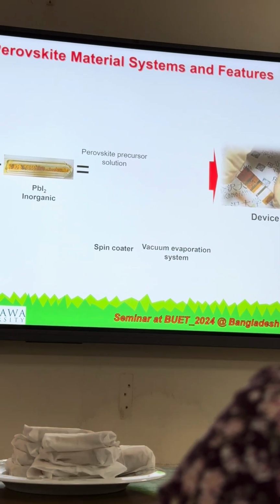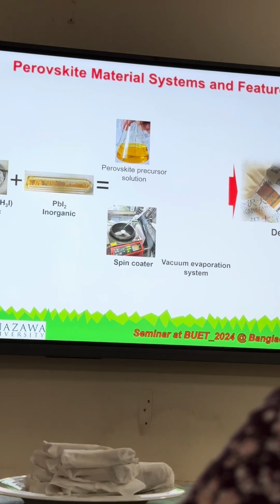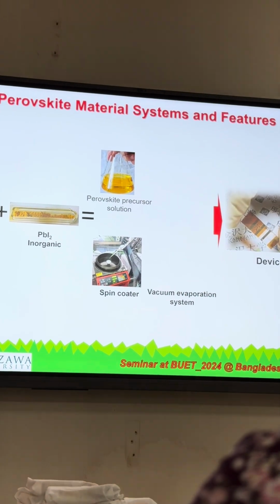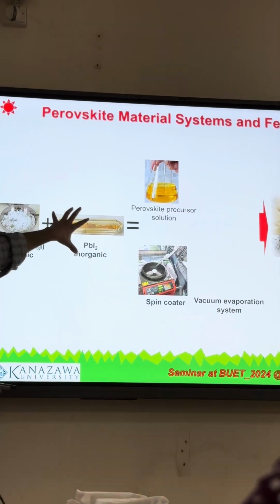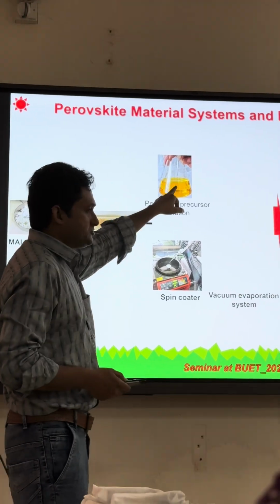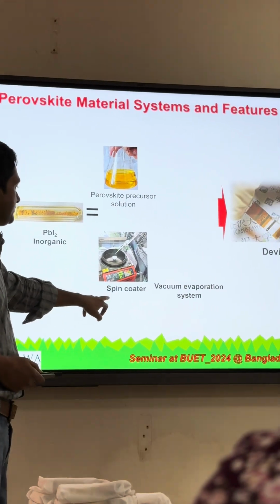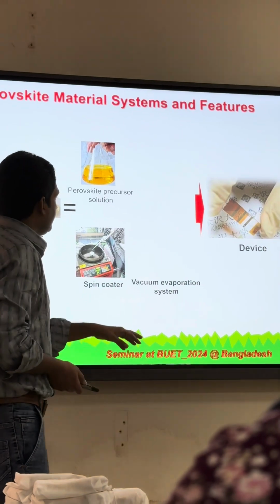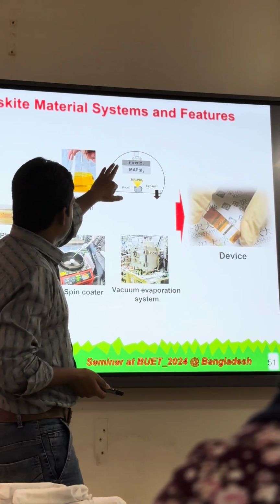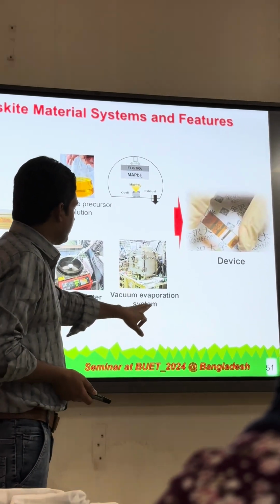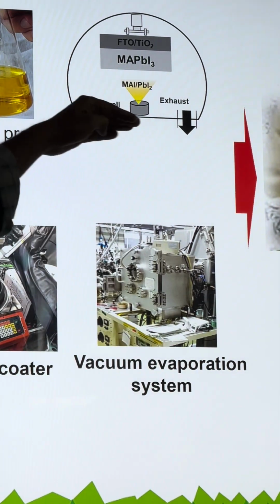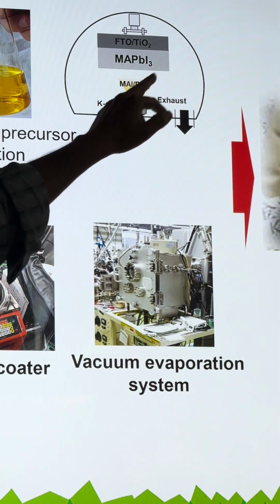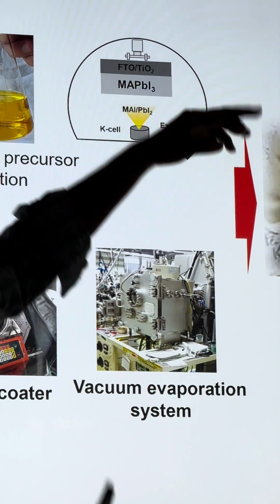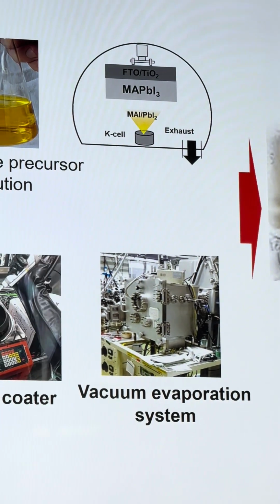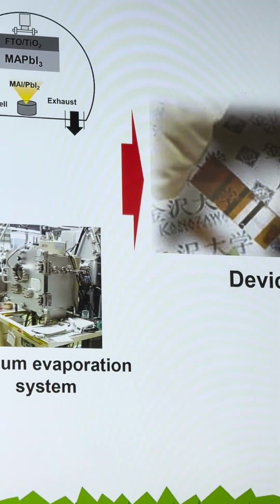So here you can see these are the organic and inorganic materials. We combine them and make the solution, then just spin coat, and we can make the thin film. In addition, we can have a vacuum deposition system. I mean we can apply heat to the organic and inorganic material, and then finally we can make a very thin film, and then fabricate the device.